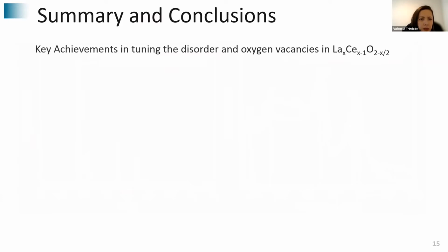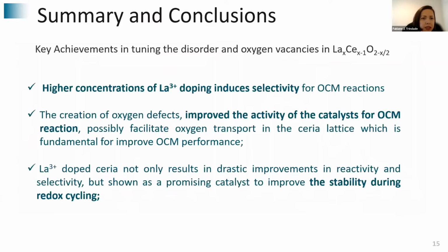So I will briefly summarize the key achievements of this work. Higher concentrations of lanthanum induce selectivity in the OCM reaction. Also, the creation of oxygen defects improved the activity of the OCM reaction, possibly due to the transport properties, which is fundamental for OCM performance. So lanthanum-doped Ceria not only results in drastic improvements in reactivity and selectivity, but also shows a promising catalyst during redox cycling, because this catalyst is still stable.